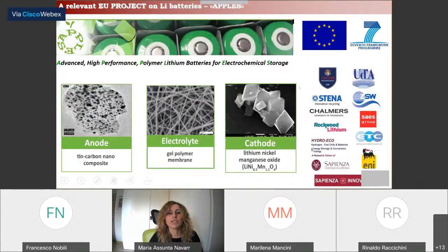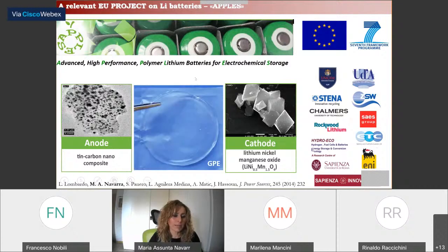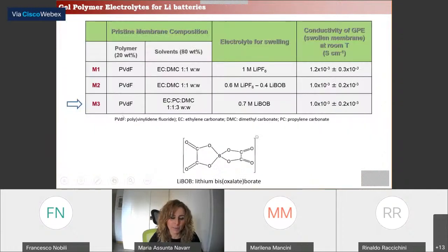Then, as I already mentioned at the beginning, an important project, for me at least, developed in collaboration with the University of Camerino was the Apples project. In this case, a polymer lithium battery prototype was developed with a tin carbon anode and a spinel cathode. And the main task of us in Rome was the development of the gel polymer electrolyte, possibly avoiding the use of fluorinated lithium salt.